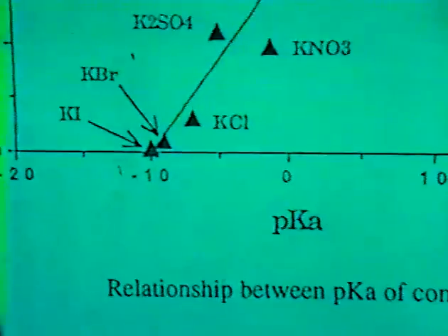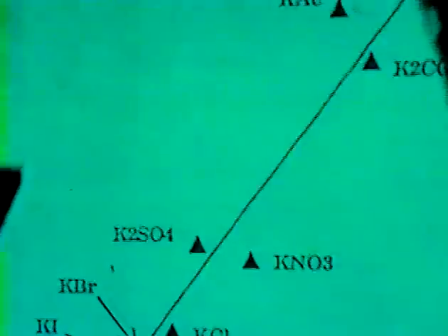So what are the variables that separate this effect? One correlation we found was between the activity for alcohol formation and the pKa values of the conjugate acid of this compound. Namely, the alcohol formation promoters had high positive pKa values. On the other hand, chain growth promoters had negative pKa values. So this is certainly a variable you have to consider.